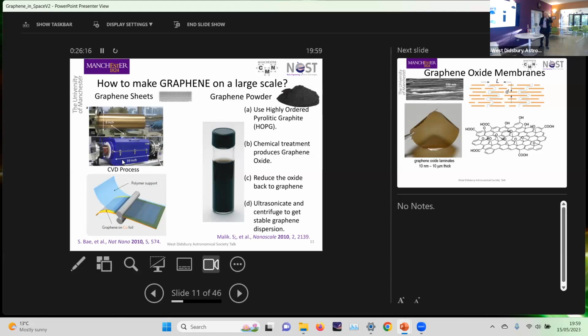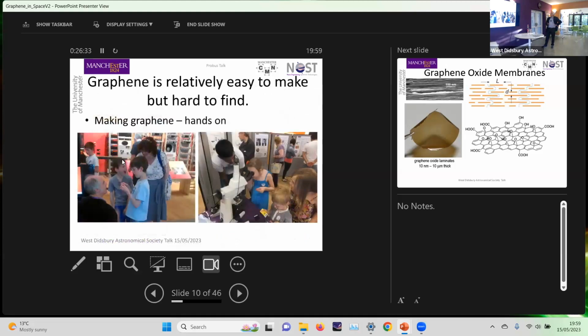And if you use a centrifuge, you can actually separate out the light layers from the heavy layers. So you can make sure that you've only got, say, single layer graphene, the very lightest layers, and then you get 2-layer, 3-layer, 4-layer, and so on. So it is possible to separate these things out.